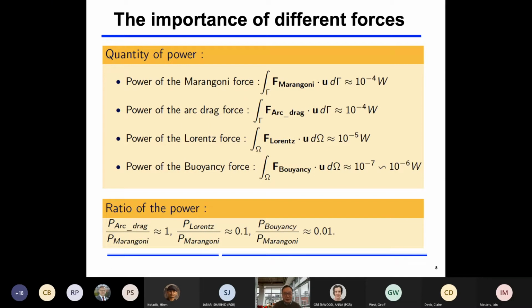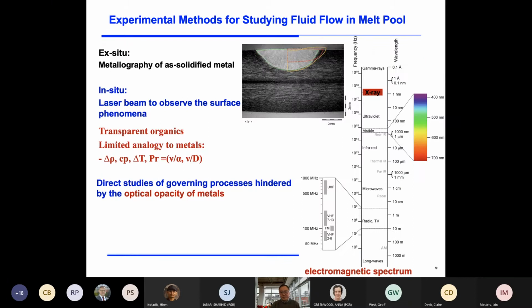The rule of thumb, you probably have this kind of ratio of the force acting on your weld pool. Arc drag force is probably in the same order of Marangoni force, and then Lorentz force is one magnitude less, and buoyant force is probably two magnitudes less, right? So those are the main forces acting on the weld pool, and so how to characterize them, right?